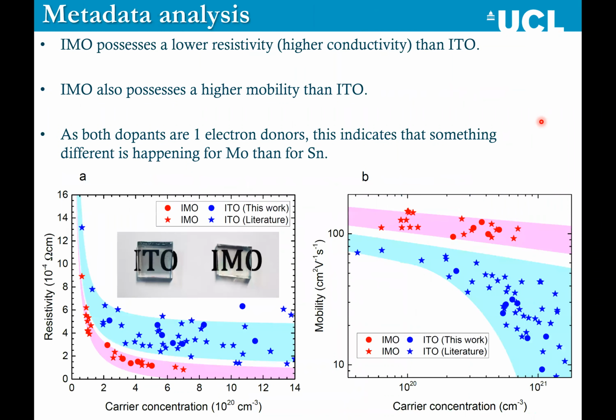So we wrote a large grant proposal to the EPSRC, backed by one of the biggest glass companies in the UK, because they were interested in understanding how they could make better transparent conducting coatings for the glasses that they sell. And we actually did a large amount of research into molybdenum doped indium oxide. And we found that there were about 30 papers in the literature at that point. And we added all that data onto our own data from extra careful growth